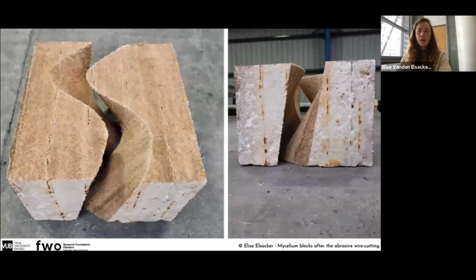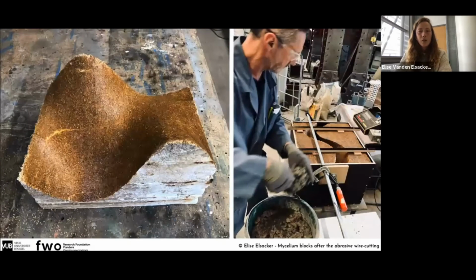for example, for different functionalities, like a formwork for concrete. So here, I shipped those back to Belgium, and then I applied a beeswax directly on the surface, and this was to avoid the absorption of the poured concrete. So concrete would be poured in between; here a 10 centimeter layer of concrete was poured into this.